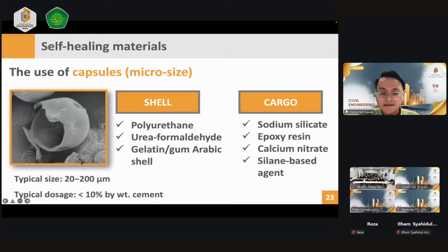And the typical size of the microcapsules is between 20 up to 200 micrometers, which is very small. And normally we use these microcapsules with a dosage of below 10% by weight of the cement.